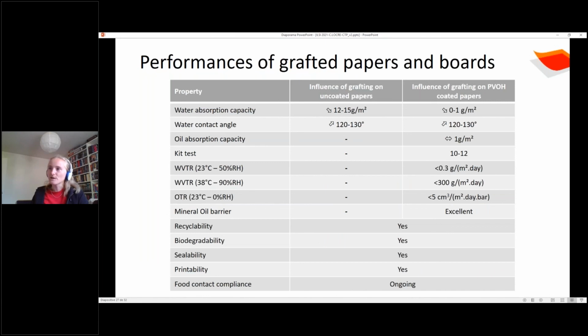And speaking of performances here of grafted papers and boards, here are some numbers of the barrier performances and other performances that can be reached. As you can see on uncoated papers, the idea is really to improve the hydrophobicity of the material, so to really lower the water absorption capacity and to bring a high water contact angle of the material. And on PVOH coated paper and board, the water absorption capacity is even more significantly reduced. So we have an excellent barrier to water, excellent water repellency. We keep the excellent grease barrier of the polyvinyl alcohol.